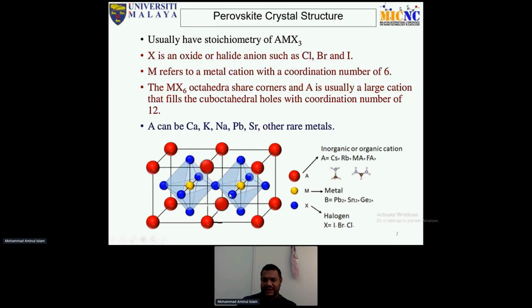And M is the metal, basically the metal cation, with coordination number 6. The metal cation could be lead. Primarily people use lead halide, lead iodide. Later on, because lead is toxic, they thought we can change to tin and germanium. But one important thing is that when we change from lead to tin or germanium, the efficiency degrades. So research is also going on over here.